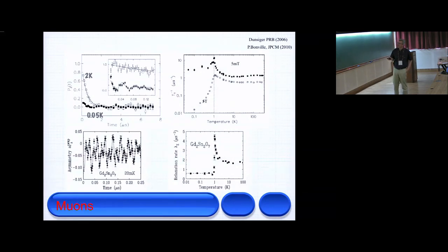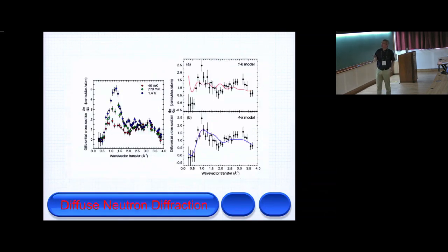In the stannate, it seems to be a very low number, but quite flat and not 0 in this relaxation rate. In the titanate in 0 field, it's up here, and we can see that these are real spin dynamics. These dynamics are fluctuating. We could pin them with an applied field of 5 Tesla, and you quench this persistence. So there's something there. Neutrons, we went to polarization, and this is one way where we can look at the nearest neighbor interactions, for instance. And we can then look at the 1-k and 4-k model and say, well, maybe the 4-k is more likely.